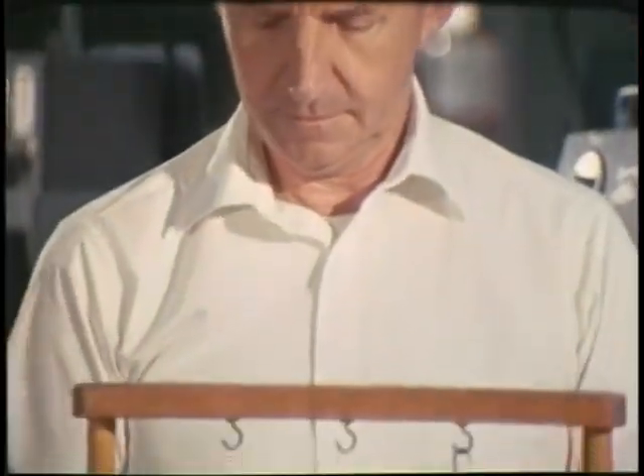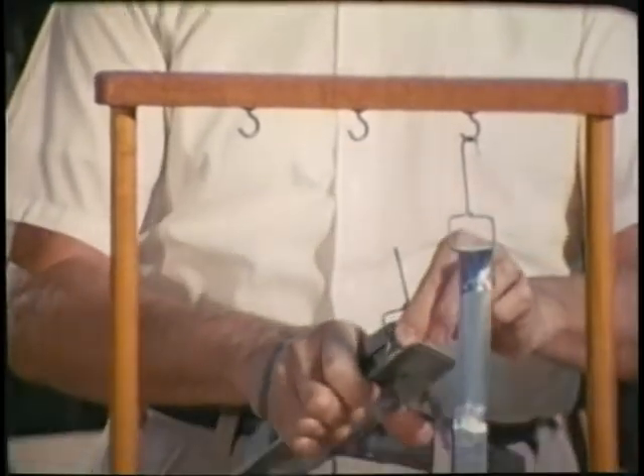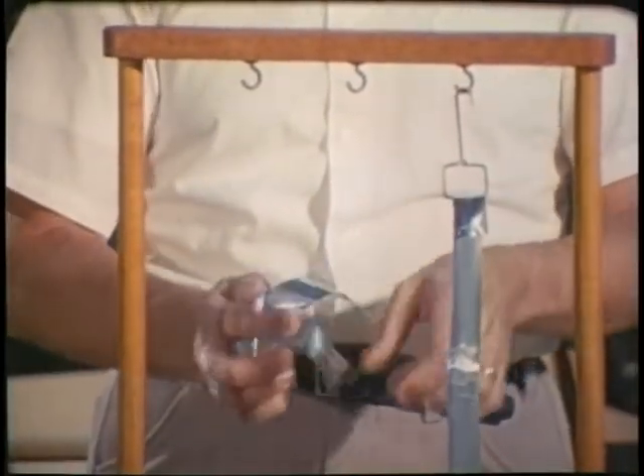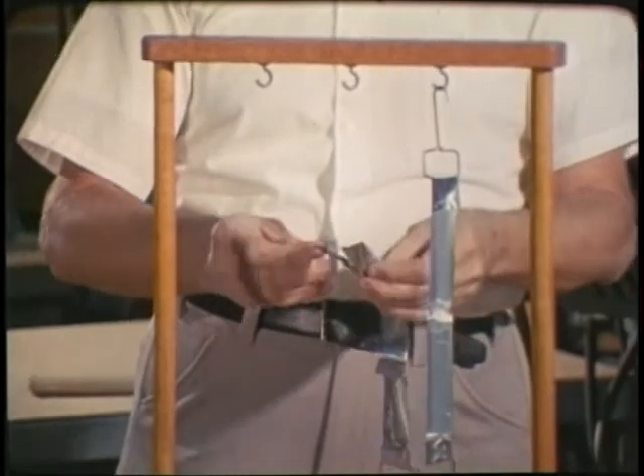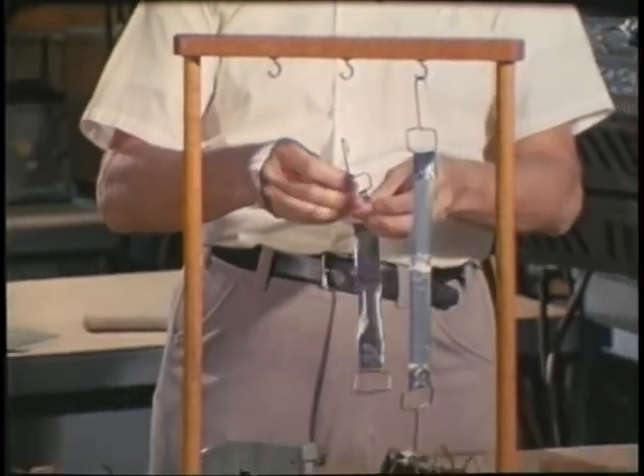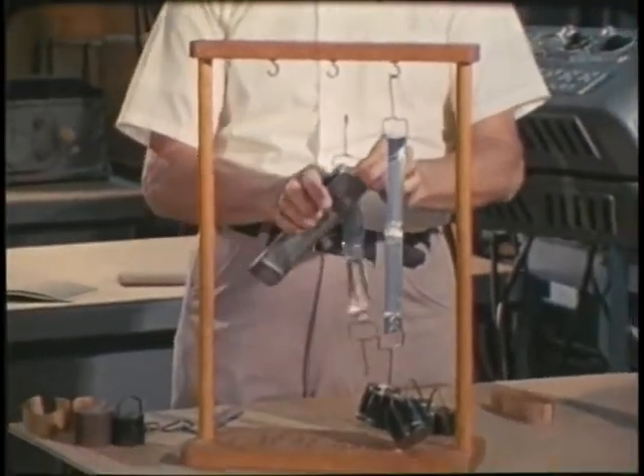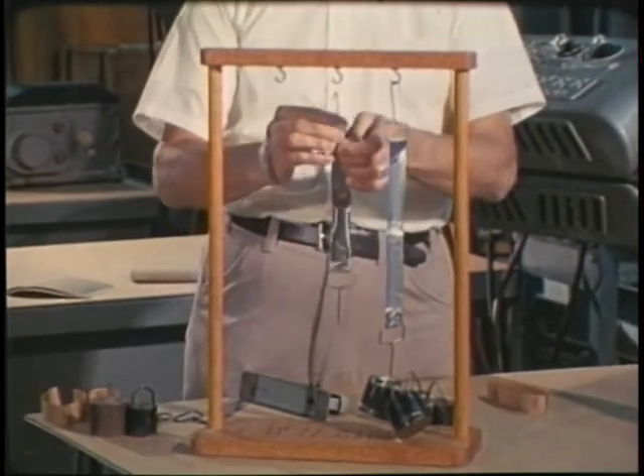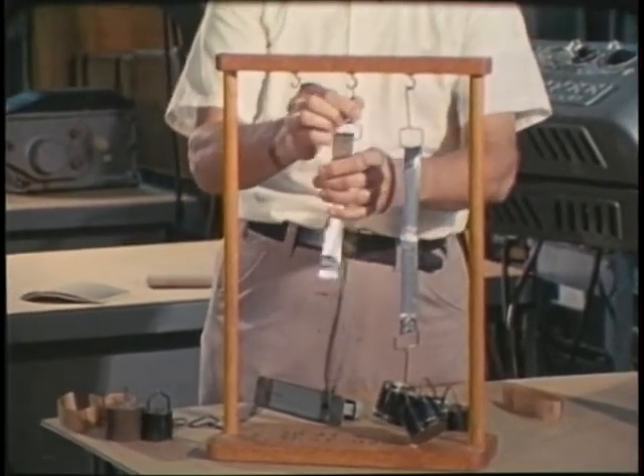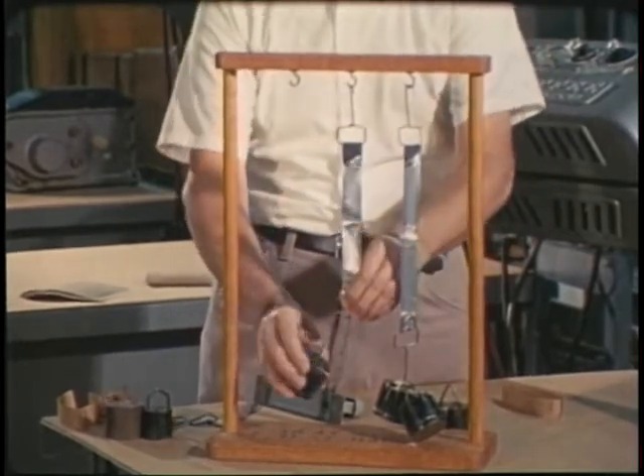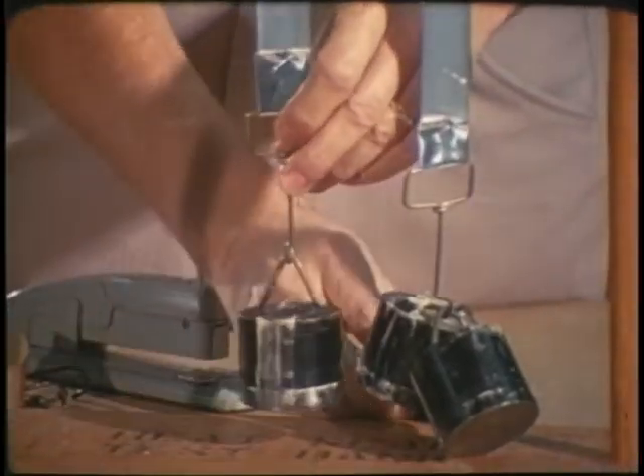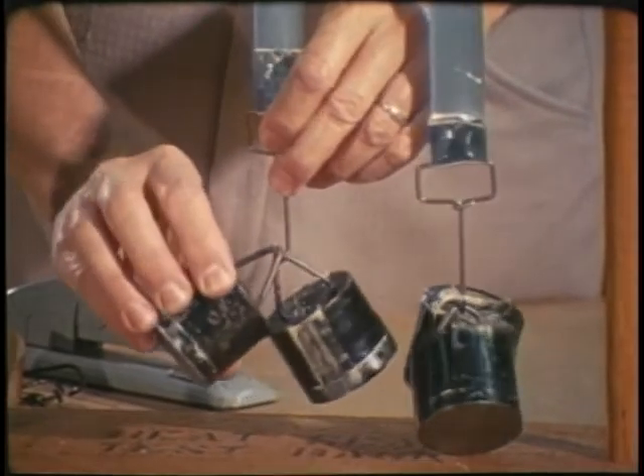The heat-sealed seam strength test must always be done according to established standards, preferably at room temperature and with static load weights as specified. If the temperature in the test area exceeds 90 degrees Fahrenheit, a 5% reduction in the static load is permitted. Partial separation of the seal is acceptable within the first 2 minutes of the test, but any separation of the heat-sealed area during the final 3 minutes of the test is cause for rejection.